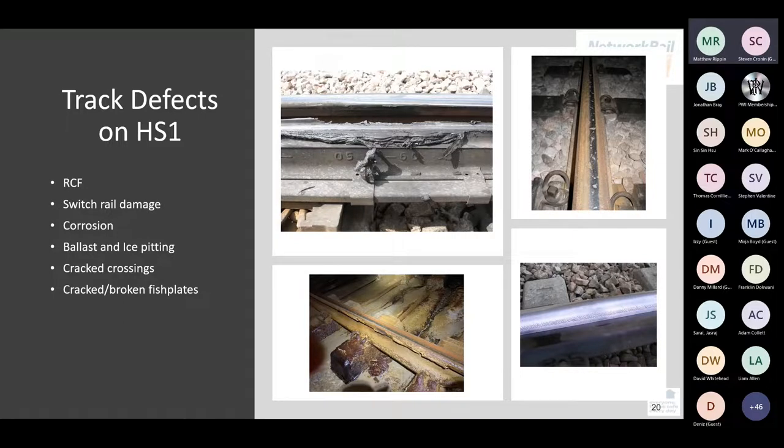What we are now seeing is that as the switches aren't breaking, they are wearing, and we're seeing a shift towards P8 type failures. So we're doing work to better understand the difference in our wheel profiles, where the critical limits actually sit, and how best to manage them through our grinding and management of steering forces. To give an idea of orders of magnitude, our trains are designed for switches with a radius around 3,500 metres, and we're then running them on a radius of 350 metres.